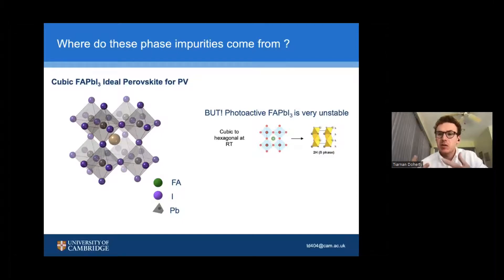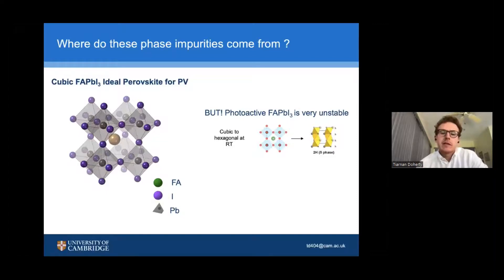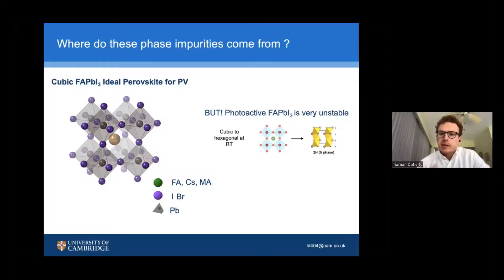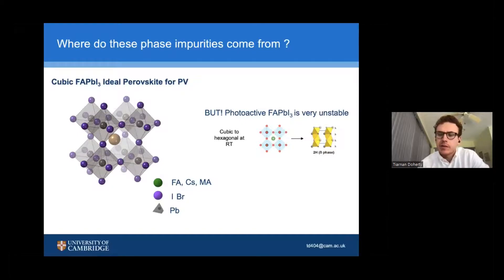The difference is that in FAPI the entire film quickly converts into hexagonal phases, whereas in state-of-the-art compositions it's only very local regions. These state-of-the-art compositions arose because people realized that adding cesium and methylammonium to formamidinium and including them in the perovskite structure could macroscopically stabilize a material very similar to FAPI, with similarly ideal properties for photovoltaics, that didn't seem to transition to hexagonal polytypes. What we now know is that hexagonal phase impurities can still form on the nanoscale, where they eventually lead to performance losses and long-term stability issues.